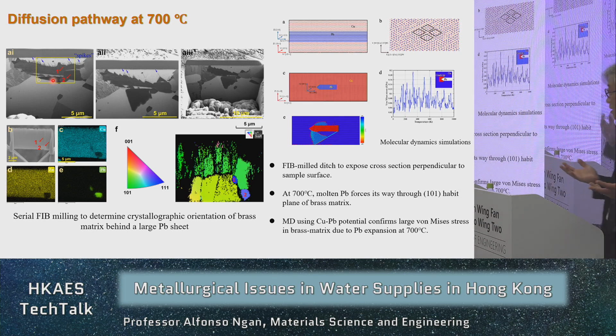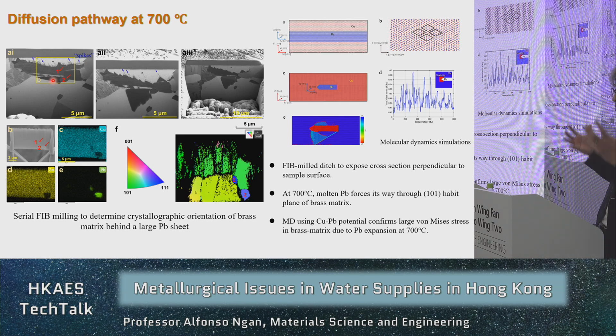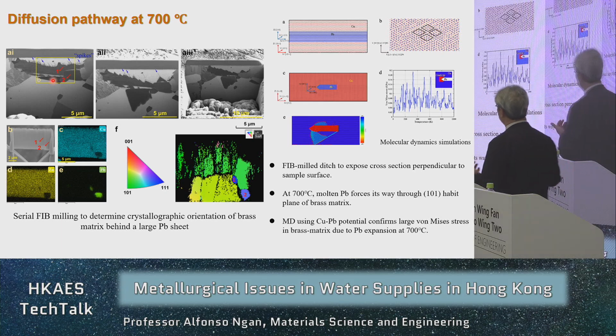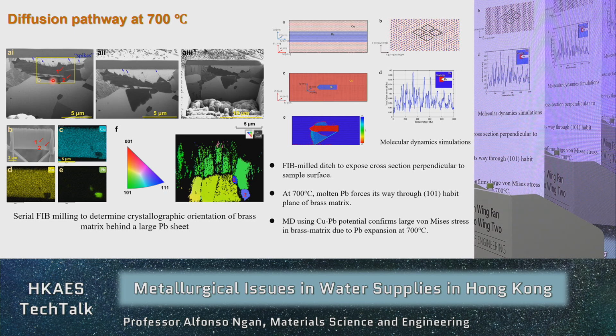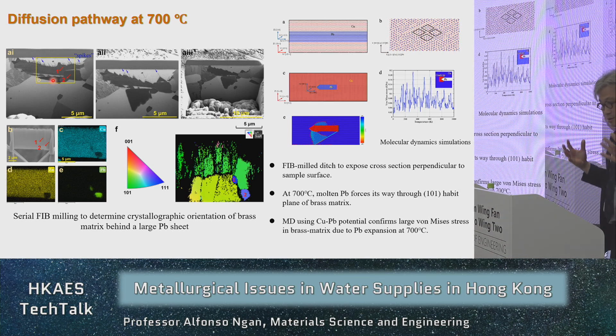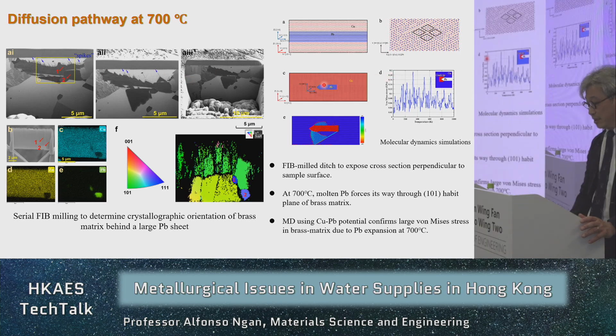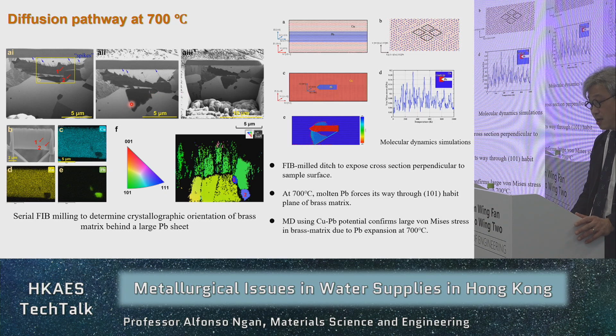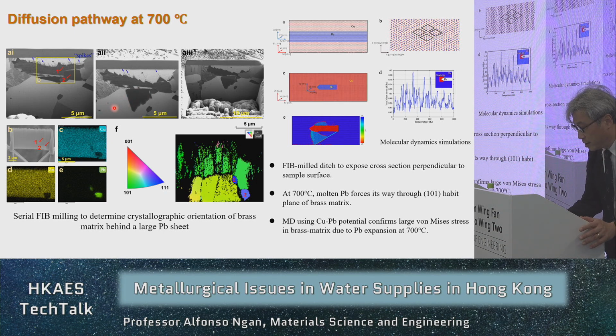All right, so why is the lead doing that? Obviously, if you heat up to a high temperature, the lead will melt and expand, right? So the expansion actually causes a lot of stress. If you have a small particle to start with, this expansion will stress up the neighborhood, and it will actually deform the copper. So therefore, the lead particle will now become a sheet. All right, so that's quite interesting. And there is a certain crystallographic orientation relation between the lead and the copper as well. So that's quite an interesting pathway that we have identified.